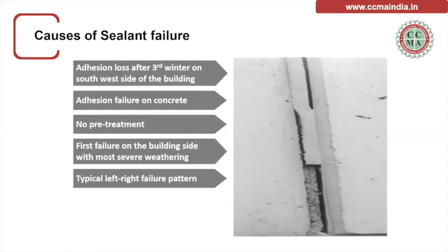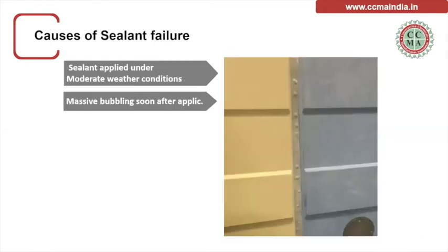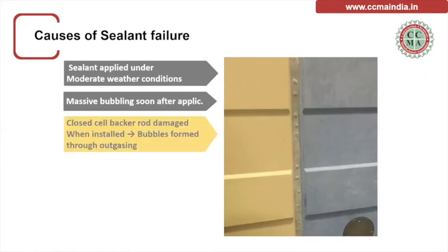Some of the typical causes of sealant failure: you have a left-right failure pattern, an adhesion failure on concrete, and this is because of poor surface preparation. Second, you can see bubbles on the sealant surface soon after application. The sealant was applied under moderate weather condition, and this is due to the closed cell backer rod which got damaged during installation, and the bubbles formed resulted in outgassing. So one needs to use a backer rod roller to insert the sealant.